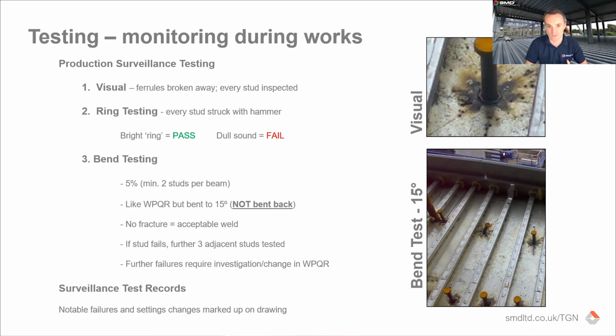A dull sound is when there's kind of porosity or fracture in the weld. Often if it's a really bad weld, if the weld's not taken, then if you hit it with a hammer you can break it off with the hammer, which clearly you wouldn't be able to do if the weld's taken correctly. But ultimately, if you get a dull sound and it sounds like it may have failed, you should always bend test that stud, but you should also bend test at least 5% or 2 studs per beam as a minimum.